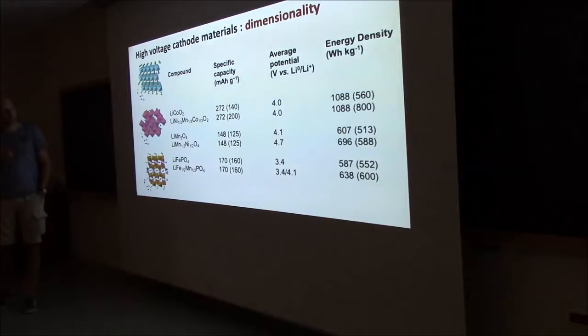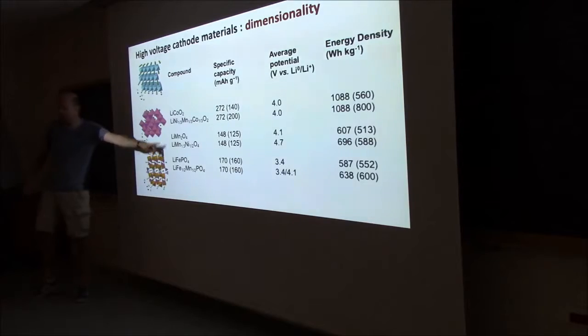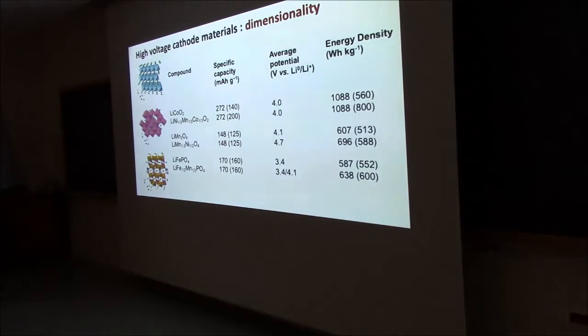What is interesting, if you look at capacities and the voltage at which these things are happening, energy densities, is that the top one is the one we're using now because it has maximum energy densities. If you replace it with some nickel and manganese, you can see it's relatively close. Theoretically, it's roughly the same that you could take out, but experimentally, people are much more successful to take more capacity out of it. Here you can see a lithium manganese oxide, that's the one I will show you. There is no cobalt in it, but you can see it has a lower capacity. Lithium iron phosphate, it's even a little bit better, but the voltage is lower.